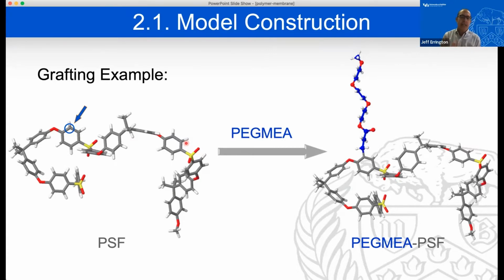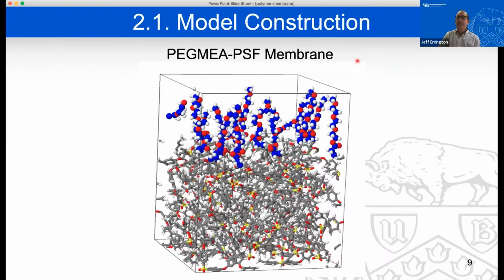And so when he did that analysis, he identified 14 different grafting sites, and we then grafted polymers onto those 14 different sites. And so in the end, a typical structure that we have looks something like this. So this is the base polymer membrane with, in this case, PEG-MEA tethers associated with it. So this ended up being the structure that we used in order to further examine the wetting properties, as well as at a later point, the structural and dynamic properties of water in the vicinity of these different structures.